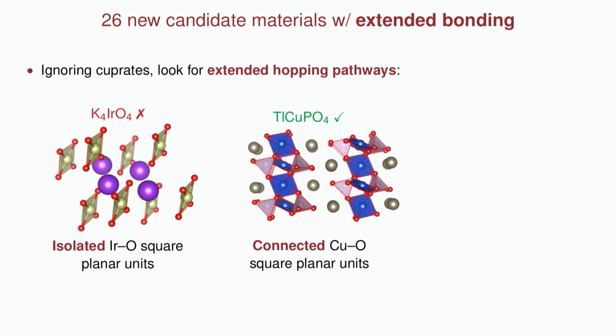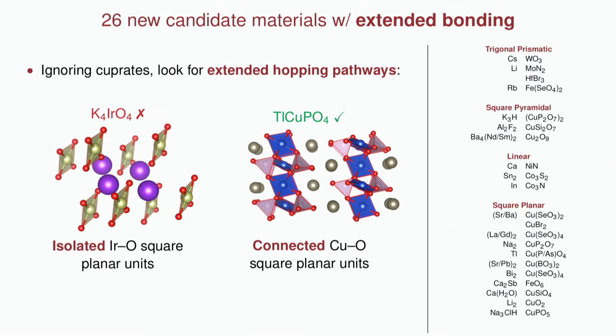So for example, for this potassium iridate compound, this has these square planar iridium oxide units, they're not actually bonded or connected in any way. So therefore, this is unlikely to give anything reminiscent of a cuprate. Whereas for something like this thallium copper phosphate, you can see there is some connectivity network between these copper oxygen square planar units. So when we consider that, now we're down to just 26 compounds. So we're quickly starting to run out of compounds. You can see we still have several coordinations here, still plenty of square planar, some linear, square pyramidal, as well as a few trigonal prismatic.